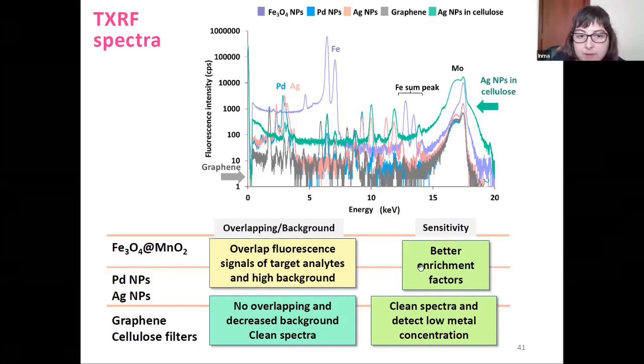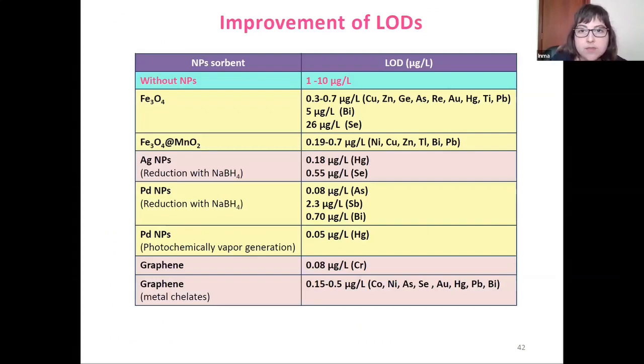We can remark that, for example, better enrichment factors were obtained when using magnetic nanoparticles and also with palladium and silver nanoparticles. Here we summarize the detection limits achieved by all of these techniques. As we can see, all of them improve the limits of detection compared to not using nanoparticles. For example, some of them are very low, 0.05 microgram per liter for mercury, which is also very interesting.